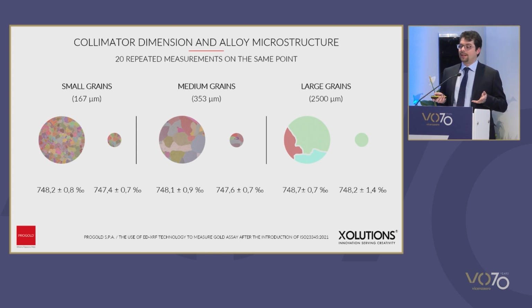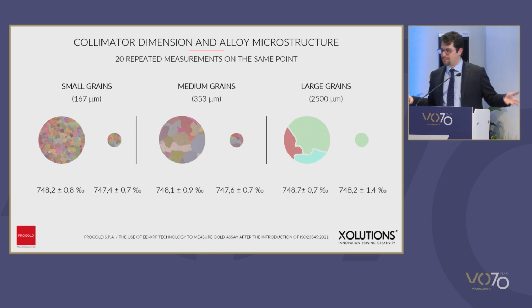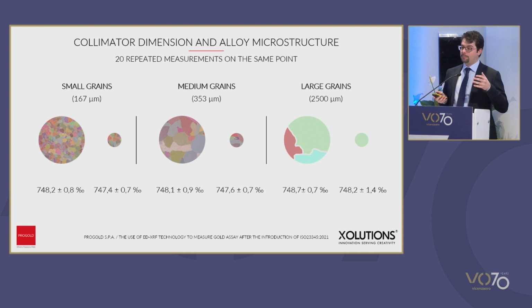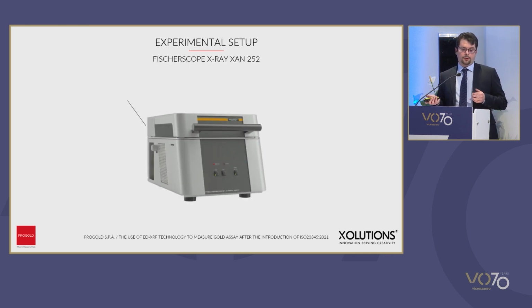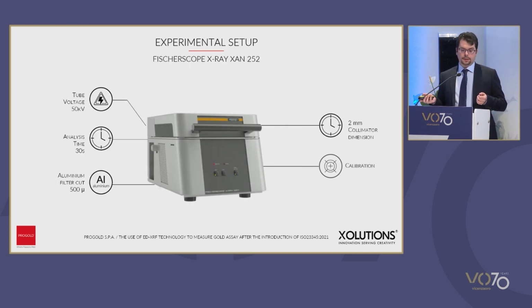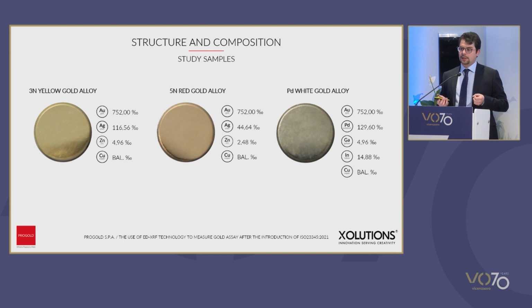Okay. Based on these results, we can conclude that it is better to use the biggest possible collimator, of course, if that is compatible with the sample. And we should pay attention, be particularly careful if our alloy has a large grain or inhomogeneous grains, because this can affect the analysis.